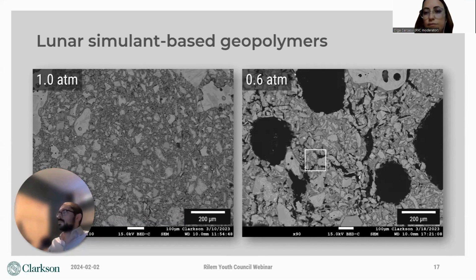The image on the right is lunar concrete formed at reduced atmospheric pressure. The lower pressure means the air bubbles don't collapse. Instead, they remain in the microstructure as it hardens, leaving the very large air voids you see here. These air voids dramatically weaken the strength of the material, which is yet another challenge we need to overcome. By the way, NASA and partners have investigated using pressurized tents to provide some artificial atmosphere during construction, but this will come nowhere near the atmospheric pressure we experience on Earth.